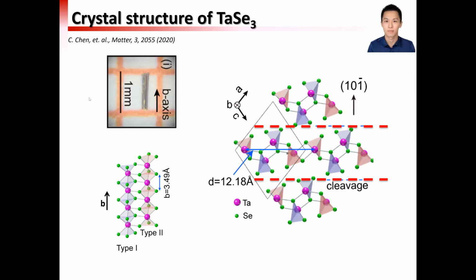With this motivation, we want to take a look at the band structure of this material. You can see that the crystal structure of tantalum triselenide is formed by two types of tantalum triselenide 1D chains along the b direction, and the crystal we grow is indeed formed by very tiny fibers resembling these tantalum triselenide wires. They loosely form a quasi-two-dimensional, three-dimensional crystal, and they can easily be cleaved.